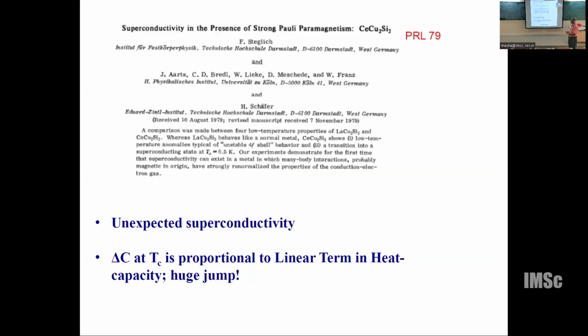And he published this paper, he sent this paper to PRL: superconductivity in the presence of strong paramagnetism. Paramagnetic terminology, because, as I told you, at high temperature it is magnetic and at low temperature non-magnetic, with enhanced susceptibility. So, therefore, superconductivity in the presence of strong paramagnetism. So this paper, in a very vague manner, reported the unexpected superconductivity, and then you could find that jump in the heat capacity.